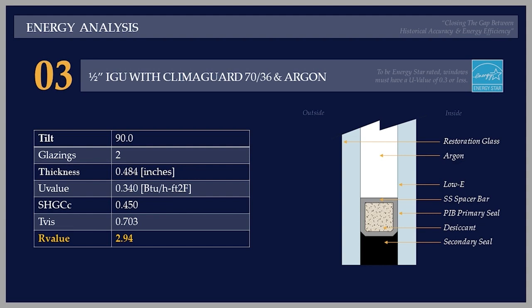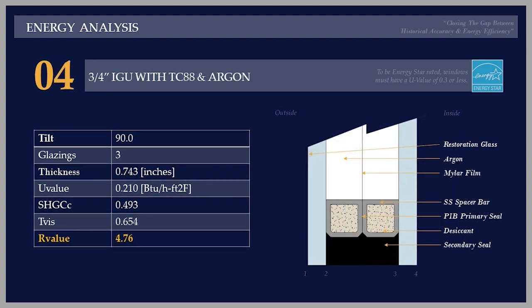Now we install an IG unit that is thicker, a 3/4 of an inch overall dimension. We integrate Eastman's Low E interface, the TC88 product, and we use argon gas. We use the Guardian 7036 Low E on the inner pane. Now check it out. The R value jumps to 4.76. That's a very good energy efficient insulated glass unit. The U value drops to 0.210 and the visible light transmission drops to 0.654. And the SHGC is 0.493. Basically, this is a very good energy efficient window, ideal for any historic application.